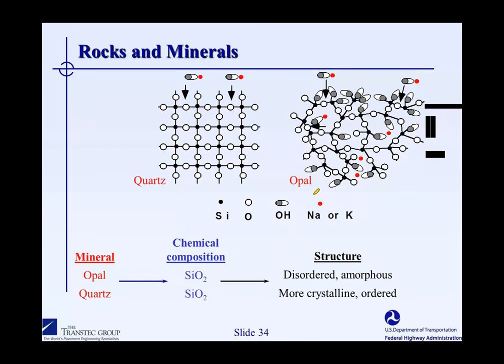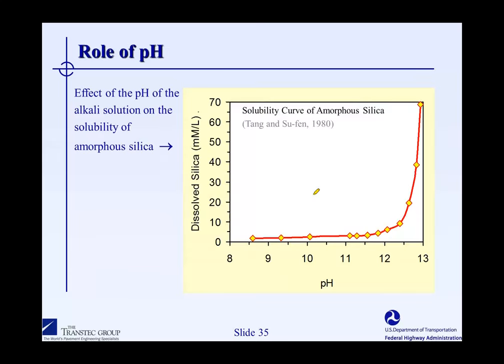So it's an important thing to realize. It's not the chemical composition of the aggregate that determines its reactivity, which is just as well. Otherwise, all silica aggregates would be reactive. But it's actually the structure of that silica that's important. The disordered amorphous silica, the glassy silicas, are more reactive than the more crystalline, well-ordered silicas. Okay, so that explains the role of silica.